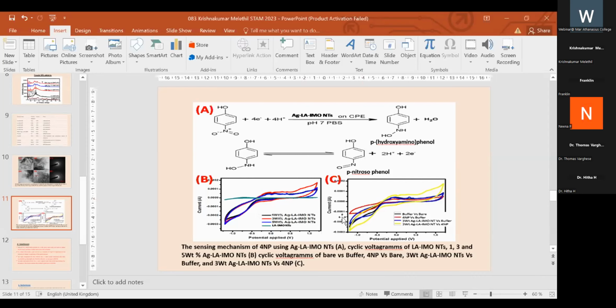And this is the electrochemical cyclic voltammetric profile. According to these profiles, we can see a reduction peak at minus 0.8 volt. It's a characteristic peak of reduction of nitrophenolate ion to para-hydroxylaminophenol. And this para-nitrosophenol is again oxidized to para-nitrophenol. That peak is here. It's not clear actually because the graphs are small.